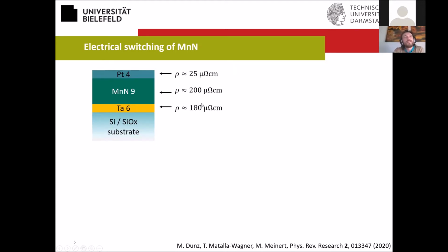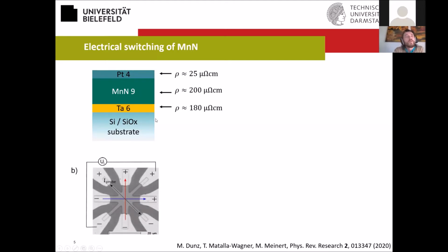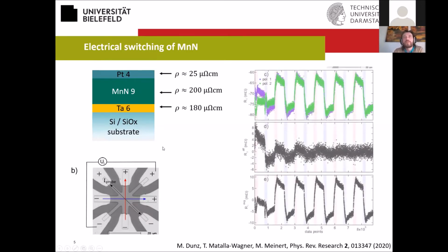The electrical resistivities are around 200 microhm centimeters for the manganese nitride and the tantalum. The platinum has about 25 microhm centimeters, which means when we apply a voltage and pass a current through the stack, most of the current is going to flow through the platinum layer. So this is our source of the spin current. We use this standard 8-arm star-shaped device pioneered by Wadley and co-workers, originally proposed for the observation of the switching in copper manganese arsenide. So this is our standard device that we use for the switching experiments.